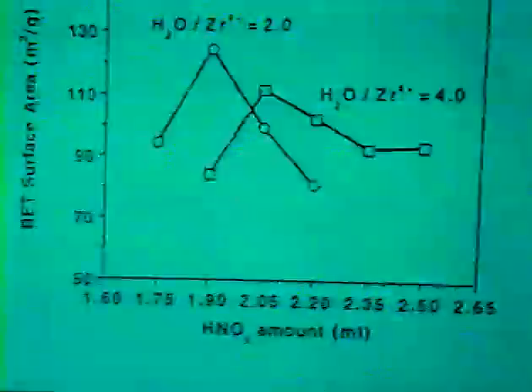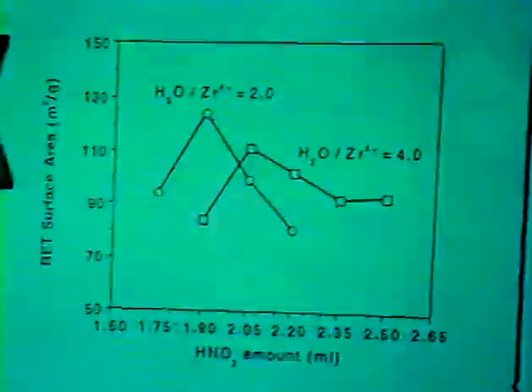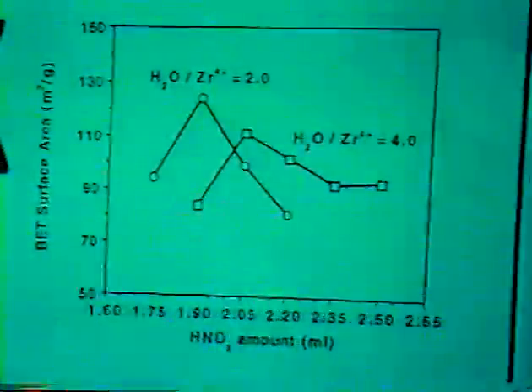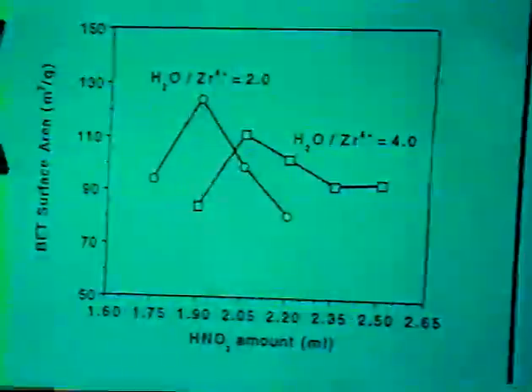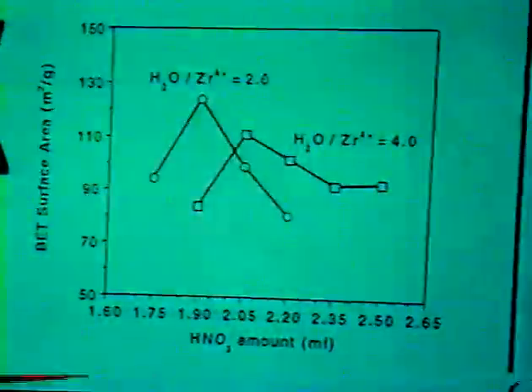What effect does it have on the physical properties of the material? First, let's take a look at the surface area of zirconia aerogels after they have been calcined at 773 Kelvin for 2 hours. What we are showing here is the BET surface area as a function of nitric acid content for the 2 series of catalysts synthesized with a water to zirconium ratio of 2 and 4.